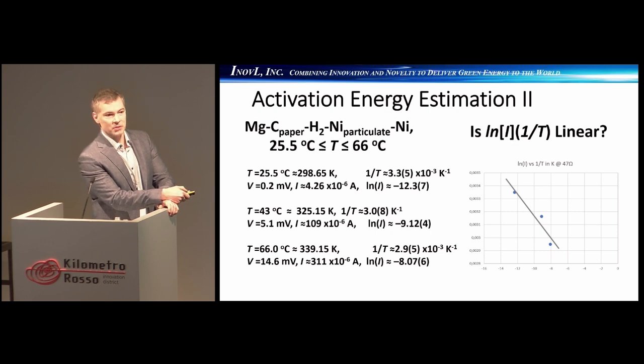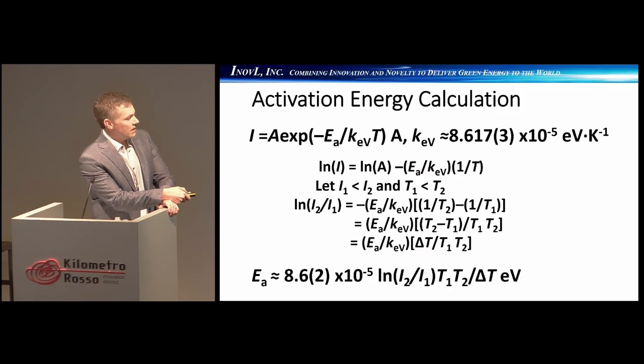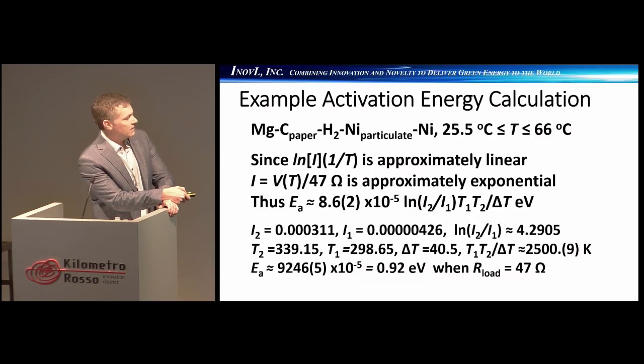So that's showing us that yes, it is exponential, and so let's go ahead and calculate our activation energy. Here's a derivation of what we're doing, the 2-point activation energy. And so at the 47 ohms, we ended up with an activation energy of 0.92 electron volts.